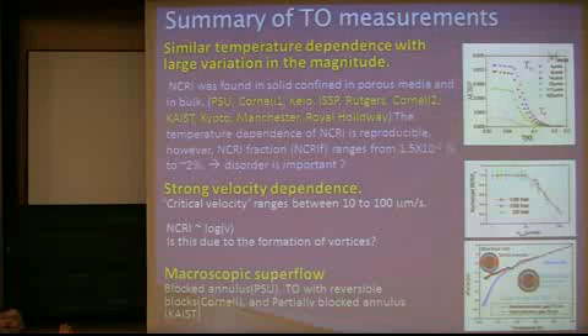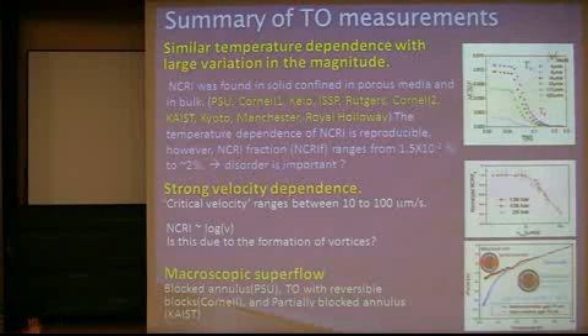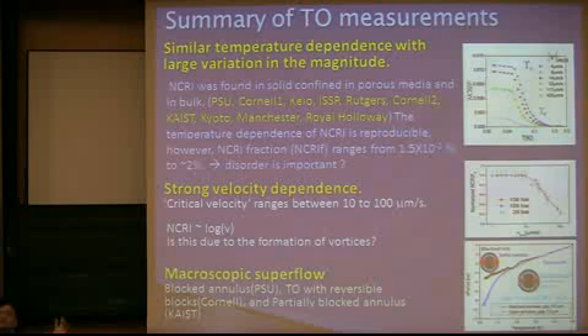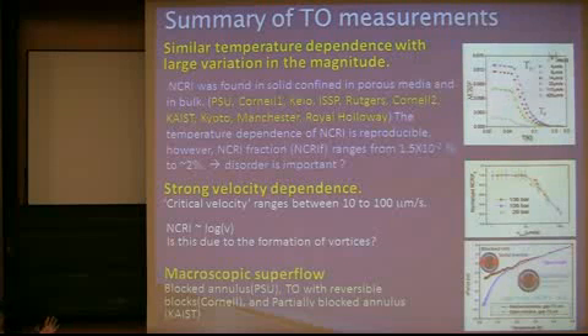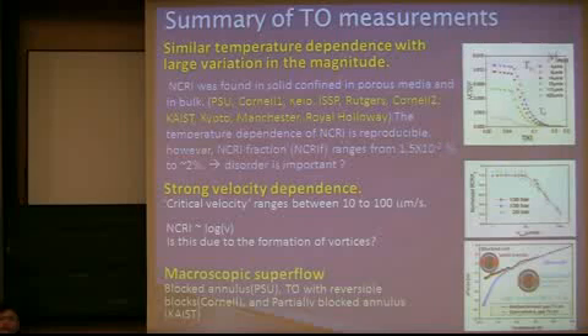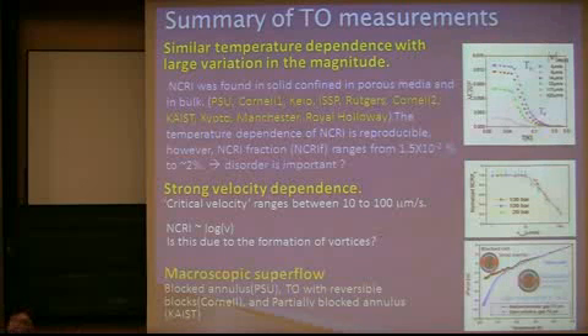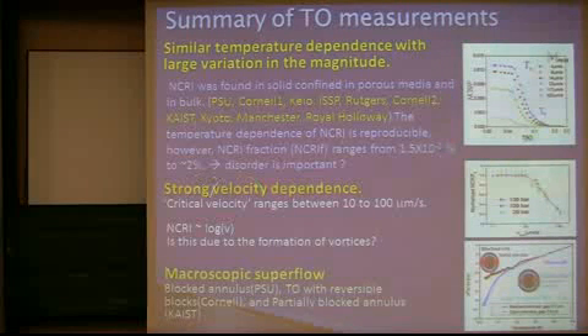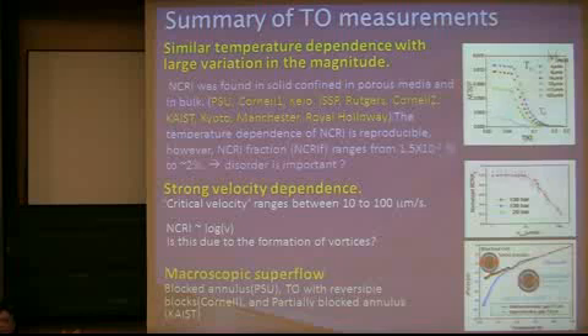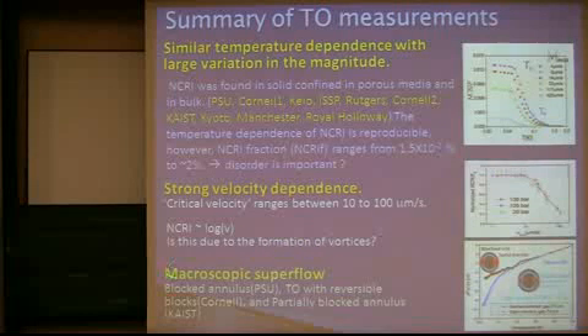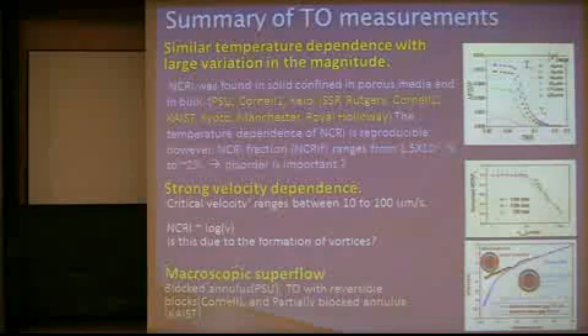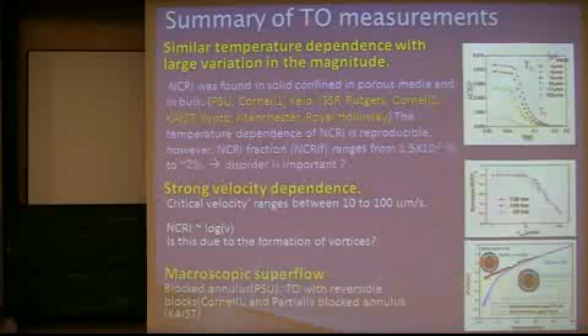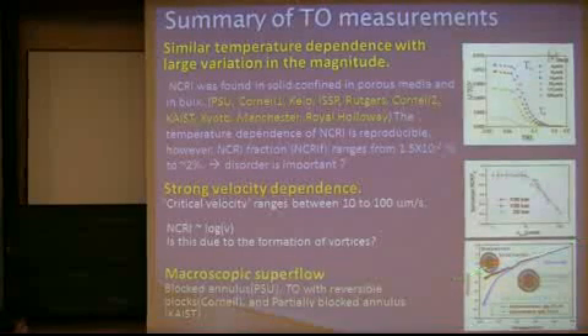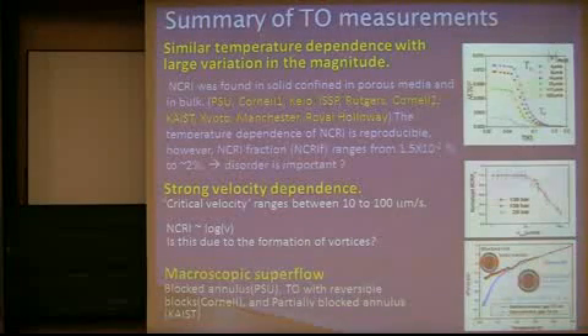After these two torsional oscillator experiments, at least 10 groups around the world reproduced this experimental result. They all find this kind of non-classical rotational inertia, the reduction in the resonant period. They also find a strong velocity dependence, and they found the non-local macroscopic superfluid: when they block the annular channel, the effect is completely gone.